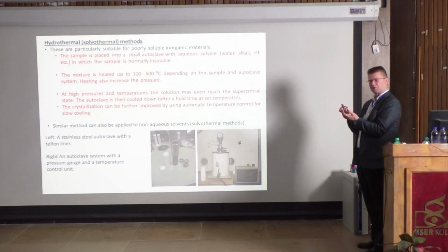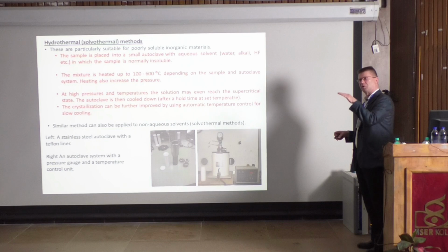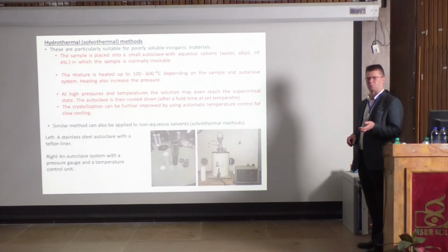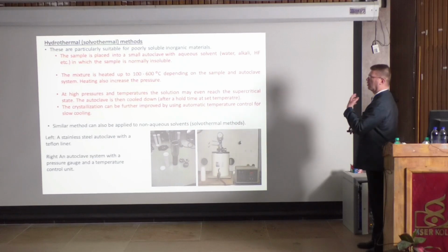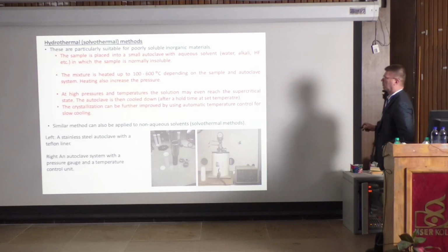all the components are solubilized, and then what you start to do, you start to very slowly cool it down. You let it cool down slowly, and the slower is the temperature decrease, the better chance you have of having good crystals. And majority of MOFs are done in this way. They can be done otherwise, but this is a very neat way to do it. Or some other complexes can be done. Typically metal complexes done like this.